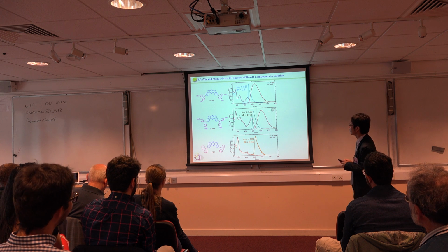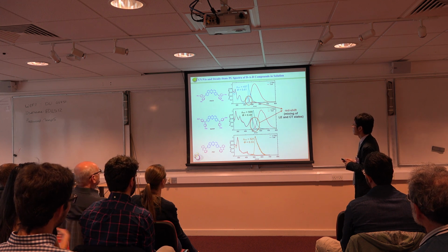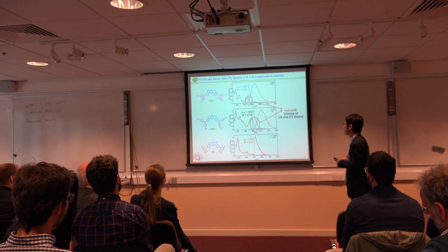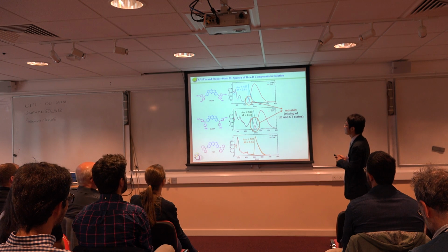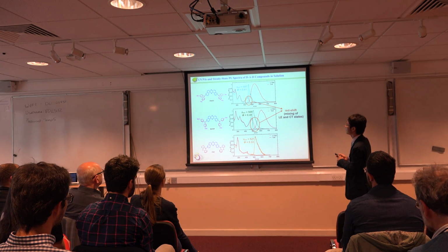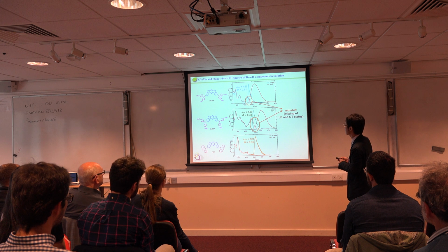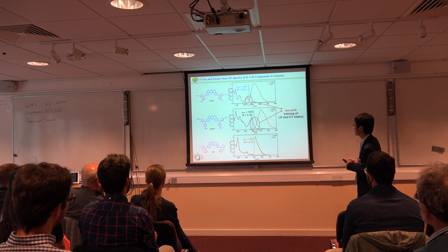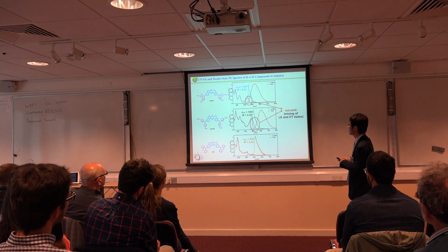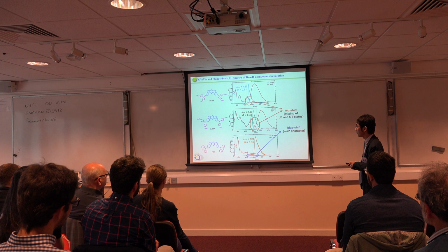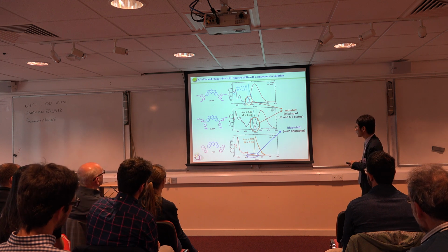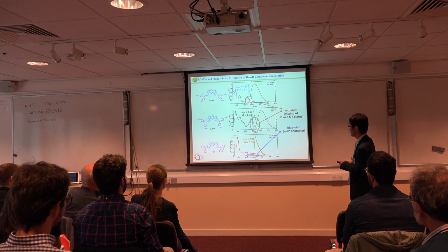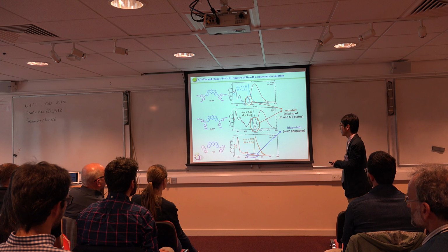So here shows the physics. In this carbazole diphenyl amino compound, as the polarity of the solvent increased, a red shift was observed, showing the mixing of the locally excited state and the charge transfer state in the polar solvent. However, in this compound, the blue shift of the absorption edge was observed, probably meaning that this transition is a charge transfer transition.